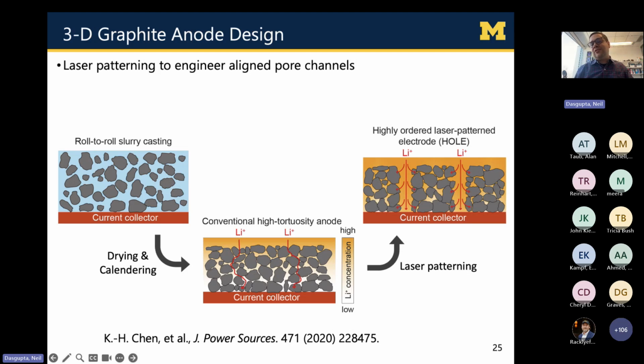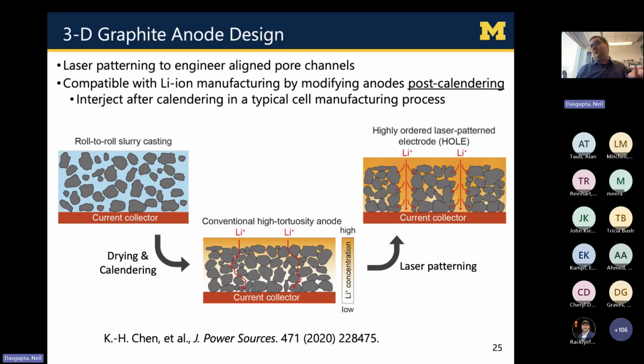And if we use a laser to literally drill holes inside the graphite electrode, these can create channels for very rapid ionic transport, and this will improve that synchronicity. This will improve the uniformity of the rate of charging between the particles, and that should, in principle, enable us to charge the battery faster. Importantly, we were also thinking right up front about manufacturing. We didn't want to reinvent the wheel by making a whole new type of battery or having to substitute a new material in. This is compatible with lithium-ion manufacturing.